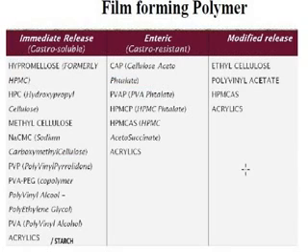So these are examples of various film forming materials or film forming agents. Suppose you want to prepare a film for an immediate release tablet, then we can use hypromellose, called HPMC, as well as HPC or methyl cellulose. Such polymers we can use for tablets which have immediate release, or normal tablets that release immediately inside your stomach.